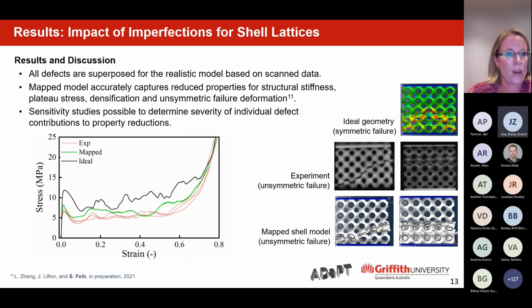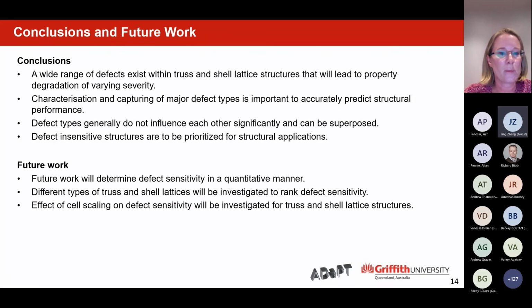So a bit about the conclusions here. It is important when we push the boundaries to capture these types of defects. Interestingly, maybe expected, these defect types do not influence each other and therefore can be superposed. So we haven't found any effects of defects acting together in some manner to further degrade properties. And with this kind of work, we can look at defect sensitivity in a quantitative manner. We can rank our shells and truss lattices, and we can also look at the effect of cell scaling.